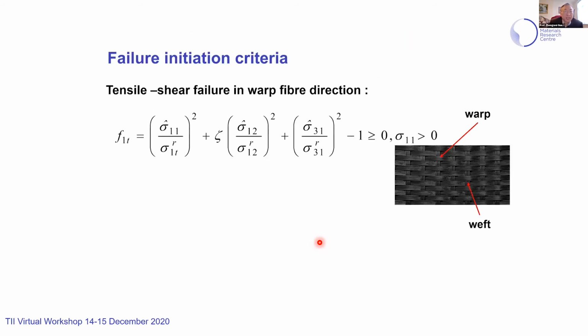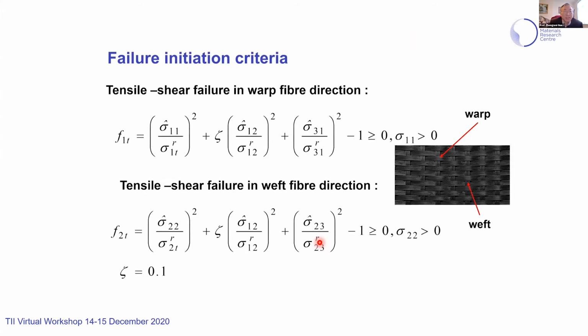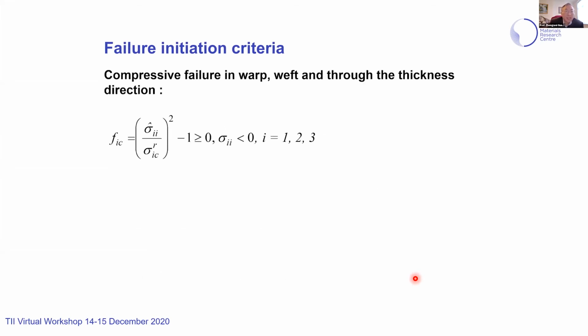This failure criteria covers tensile and shear failure in the warp direction and also in the weft direction. That is a typical woven composite, and we use this damage criteria, through the warp, weft, and thickness directions. So that's the failure criteria we use.